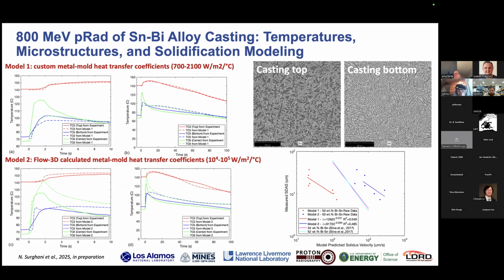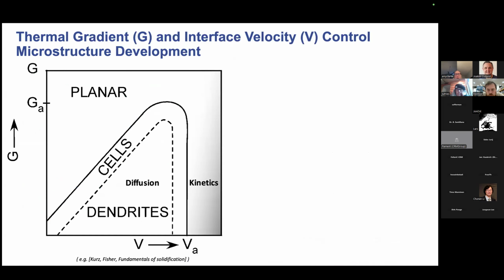We also know from the microstructure, we can look at characteristics about the microstructure, things like primary or secondary dendrite arm spacing, and we can relate things like that to cooling rate. So this is just an example micrograph of the top of the casting, which is much, much coarser than the bottom of the casting, which has a much, much finer dendritic structure. And here she's just doing some comparisons in terms of secondary dendrite arm spacing. So again, this has a lot of potential impact to better understand metal casting and to better understand casting design. And we have done some PRAD experiments looking at microstructure development as well.